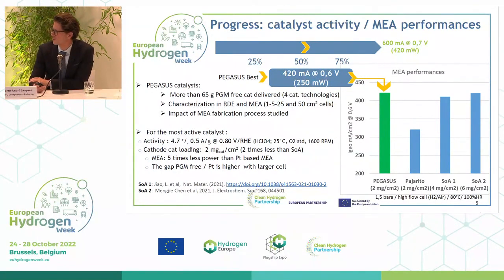The target of the project was to be able to reach 600 milliamps per square centimeter at 0.7 volts. It means 420 milliwatt per square centimeter for MEA. And at the end of the project, I can say that we reached 50% of the targets. We were able to make an MEA which gave the power of 250 milliwatt per square centimeter, so 420 milliamp per square centimeter at 0.6 volt.